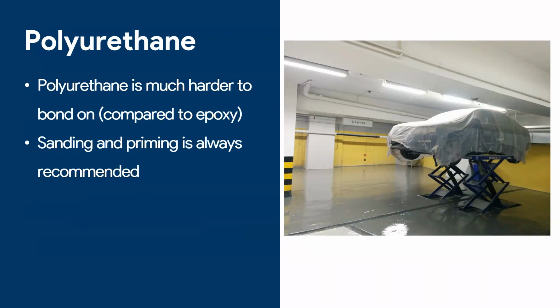And this is tricky because even though polyurethane and epoxy look similar, polyurethane is a much harder product to bond on compared to epoxy. So if you try applying epoxy on polyurethane, it will not stick as well, especially if the polyurethane has cured fully. So you may run into problems here, and you may get future peeling.